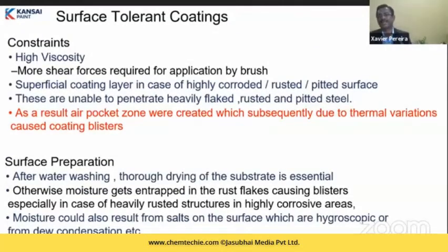went into a detailed study, and when we found out what were the reasons for blisters, what were the reasons for failures, that is the flaking, there are some of the things that the surface tolerant coatings have high viscosity. So when you apply them on highly rusted surfaces, or pitted surfaces, it is difficult for the coating to penetrate, right? And these just become a superficial coating layer. And it is also because of lack of inspection at heights. Normally, these areas are not seen by the inspector, and therefore we find the problem of flaking.